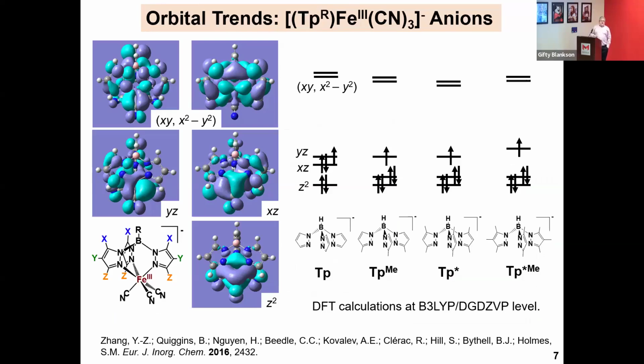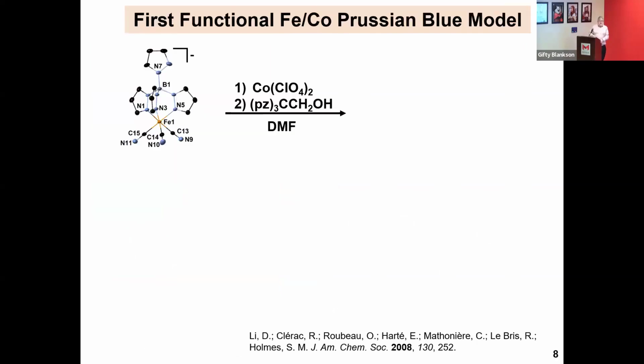And summarizing up a lot of data, very good electron donors have a very close separation between the ligand-filled orbitals and the empty metal-based orbitals, and that gives you a very low energy lambda max. If you have a big energy difference between those orbitals, you get a high energy lambda max, and so that explains the color that we see with all these. Also related to the magnetism.